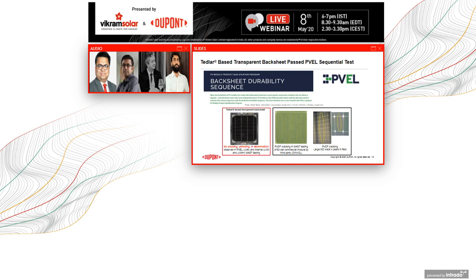Ivan did mention that all Vikram Solar modules go through the PVEL or DNVGL testing, which we also put a lot of emphasis on. In this particular PVEL sequence, or DNVGL sequence, they have now introduced a backsheet durability sequence as part of the PQP program. And this clear backsheet has been taken through the full sequence, and it's shown here on the left, without any cracking, yellowing, or delamination. So essentially no defects. However, as is pointed out in the block on the right, there are several cases of faulty backsheets that have gone through the test and have ended up showing defects, very much like defects that are seen in the field.